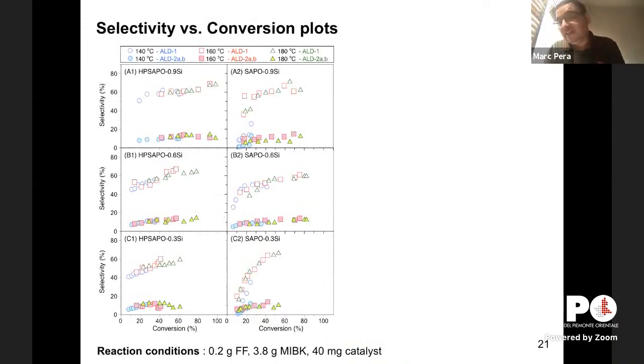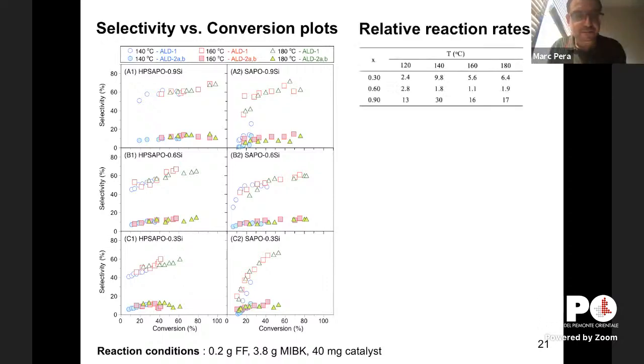We also can see the same results by plotting the selectivity conversion curves. So you see very clearly here for a standard sample, the conversion is much lower. When the hierarchical material is used, the conversion is much higher. Selectivity always with a plateau at 60%. We can reach this plateau much faster with a hierarchical material.